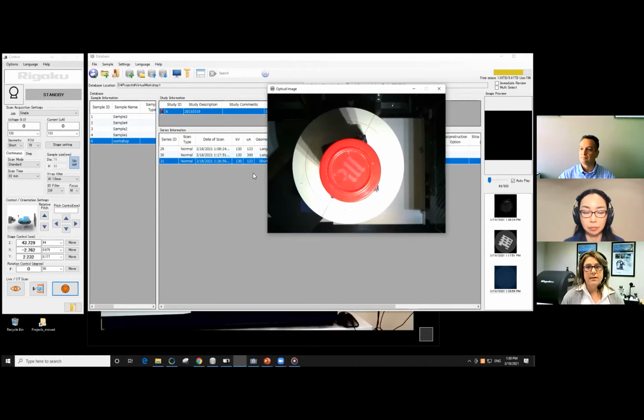So for example, I've done X-ray scattering experiments where we use a 1 millimeter capillary and put something inside. And it turns out that 75% of the X-rays are absorbed through a 1 millimeter capillary. And that's because of the water or the liquid inside. So you want to keep it to a minimum. If you're imaging insects, it really helps if you dry them. And in fact, I would fix them, stain them, dry them, and then image them.